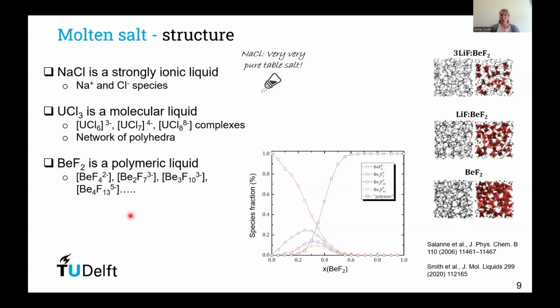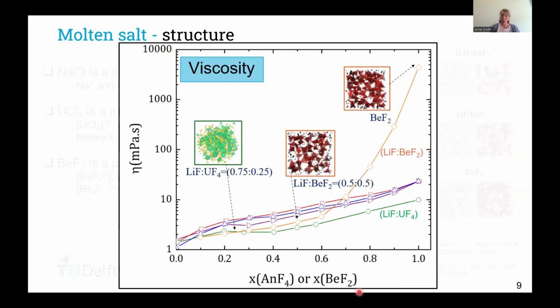At high beryllium fluoride content in a mixture, we start to form dimers, trimers, and really polymeric chains when the concentration of beryllium fluoride increases. And why is this important? This is because the structure of the salt has a direct impact on the thermophysical properties.